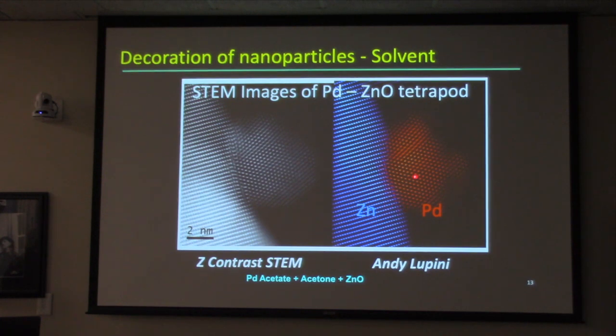It turns out that these are false colors, but the Z contrast allows you to know that this is palladium and this is zinc. The interesting thing is the interface. The zinc actually wets a little bit at the palladium surface, so there are some compounds that are formed here. And remember how I said that about the catalyst support interaction. It's really what goes on right here probably is a major part of the story. And we've started to work on that a bit with neutrons, and I'll show you the progress that we've made.